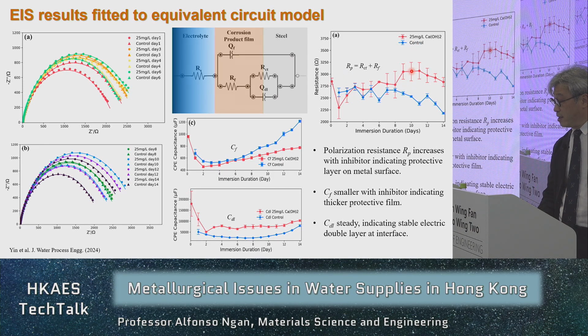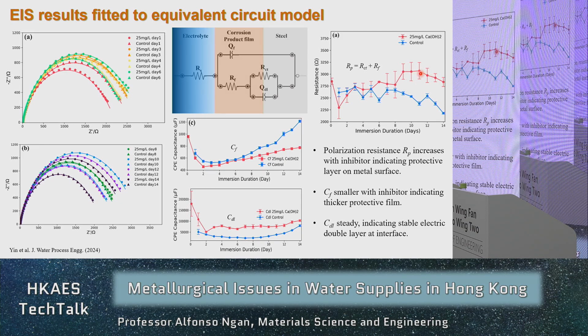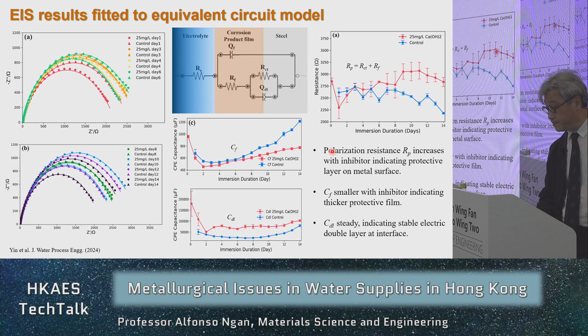The resistance in the product film as well as the resistance in the interface. So that total sum is called the polarization resistance. The red is with the inhibitor, the blue is without the inhibitor. So as you can see, for a short duration, after a week or so, the polarization resistance with the inhibitor actually becomes larger. So that explains why corrosion is smaller or slower.